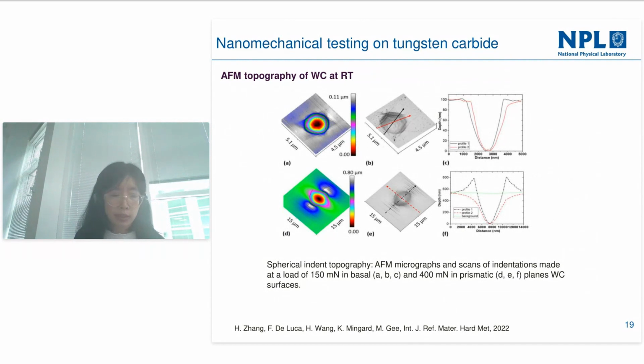So this is the AFM topography of the tungsten carbide at room temperature, corresponding to the load displacement curve in the slide above. Figures A and B show a clear six-fold symmetry in the formation of the slip traces on the basal plane, and it forms a star shape.